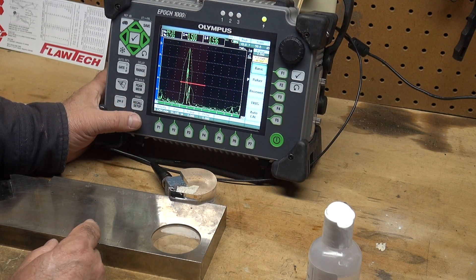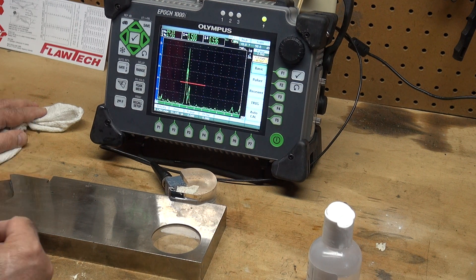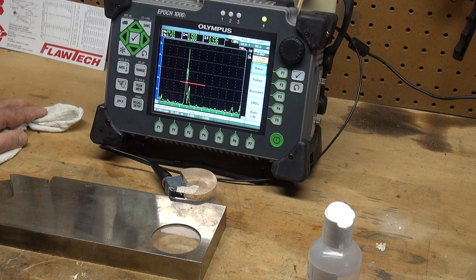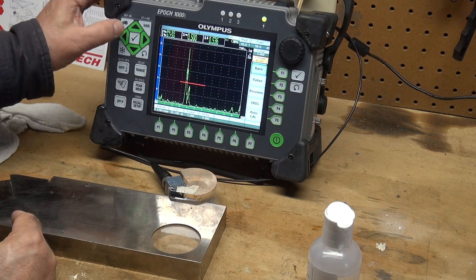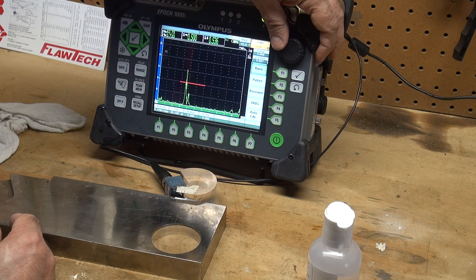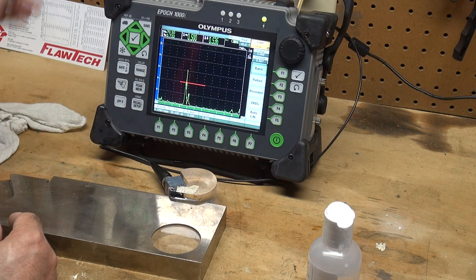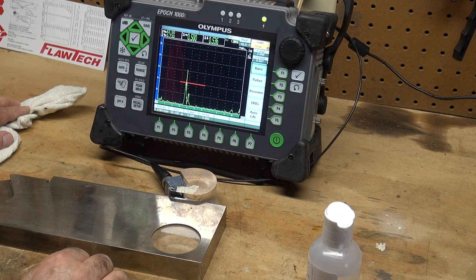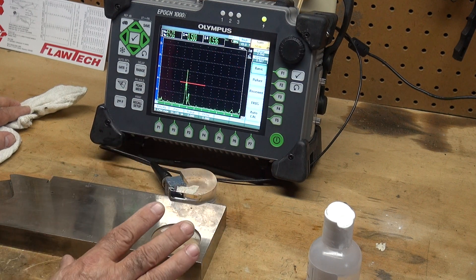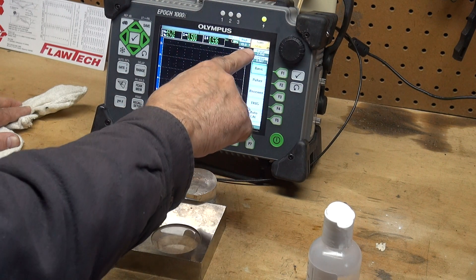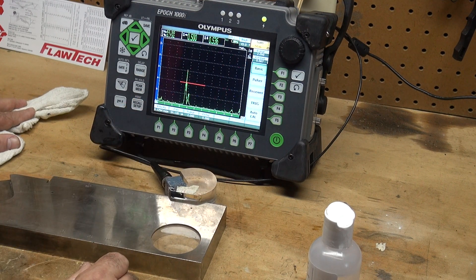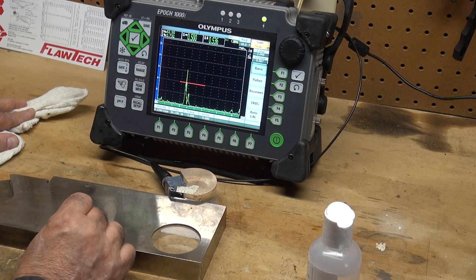That is 45 degrees shooting down to that 0.6 inch deep hole that is used for my reference. With AWS, the code says to set your reference level between 40 and 60% full screen height. I'm going to bring this down to 60% full screen height, that is your typical reference level for AWS exam. Depending on the thickness of your part, you'd have to look at the code. This is your reference dB, in this case 55.6 dB. Typically you'll run 6 to 12 dB hot depending on the code. This is your reference level and what you would evaluate indications at.